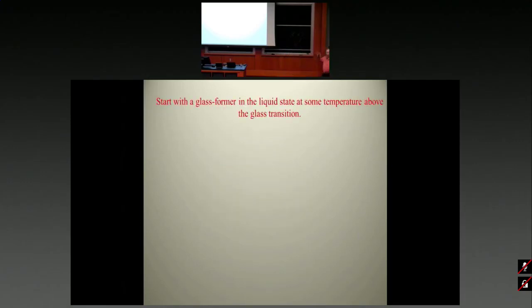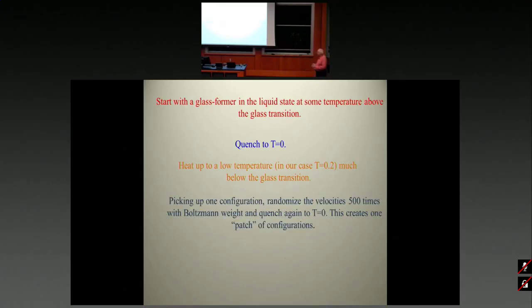So let me now explain to you how we do this on the machine. Imagine that you start with the glass former in the liquid state at some temperature above the glass transition. Now you quench it to temperature 0 using molecular dynamics or whatever you want to do. Now you heat up to a low temperature. In our case of Lennard-Jones, in Lennard-Jones units, it's T of the order of 0.2, but it's much below the glass transition. Now, at this point, you pick one configuration. You run your dynamics, you pick a single configuration, and you freeze the particles, and you randomize the velocities.